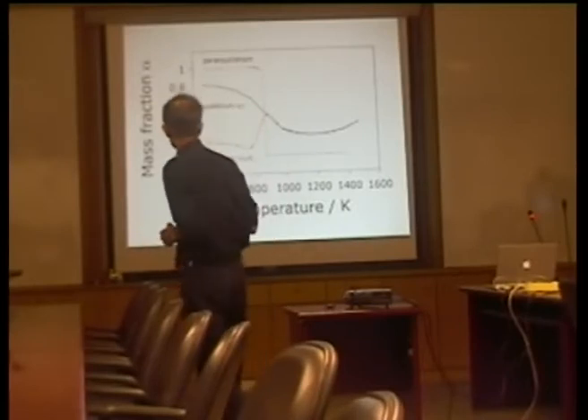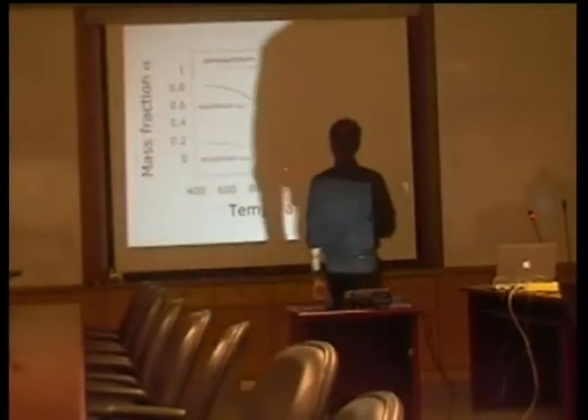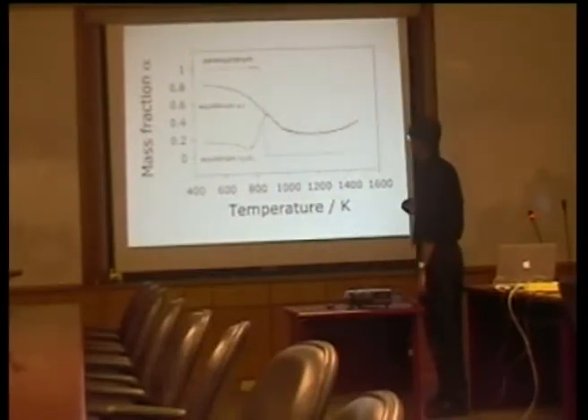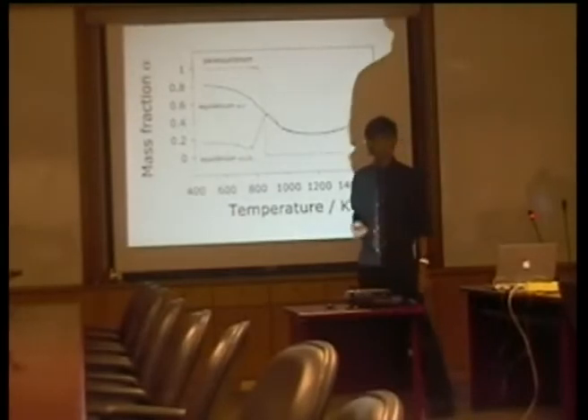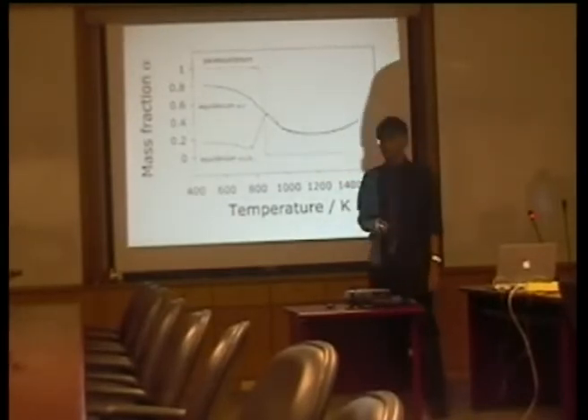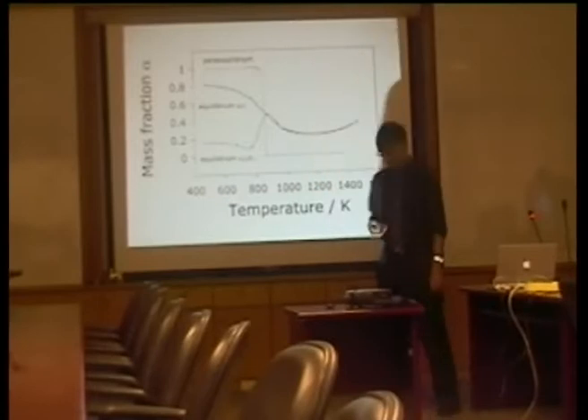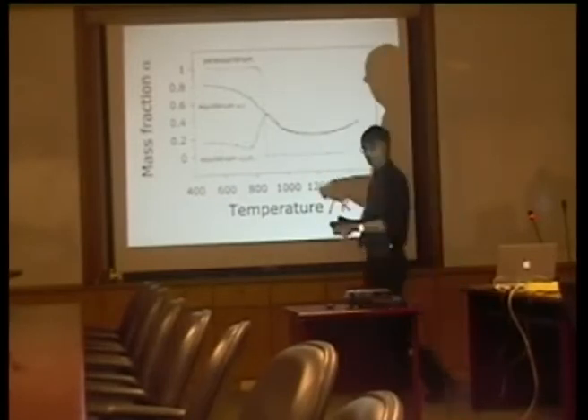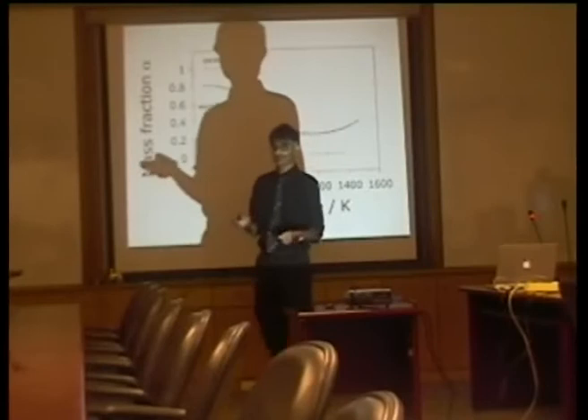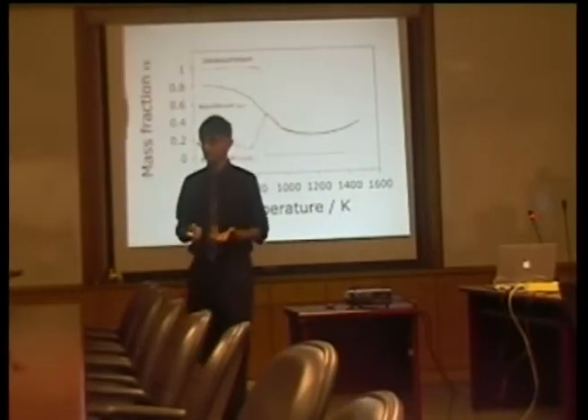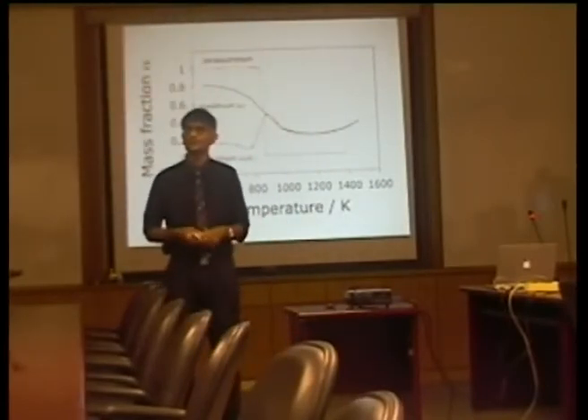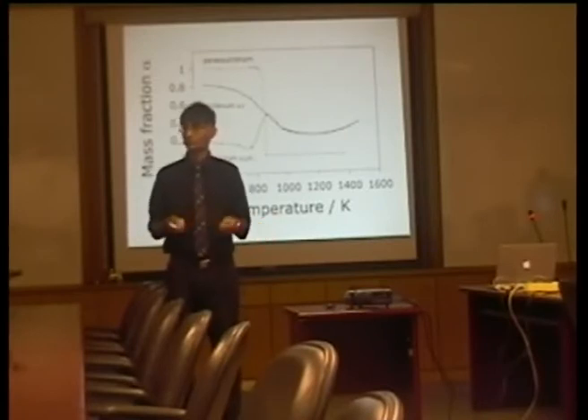If we do that calculation, then according to the equilibrium calculation, we should have very, very little austenite at room temperature. Only about 18% of austenite. But it's very unlikely that at room temperature you can get diffusion of chromium and nickel. It's impossible. It would take many hundred years for chromium and nickel to distribute between the austenite and martensite.